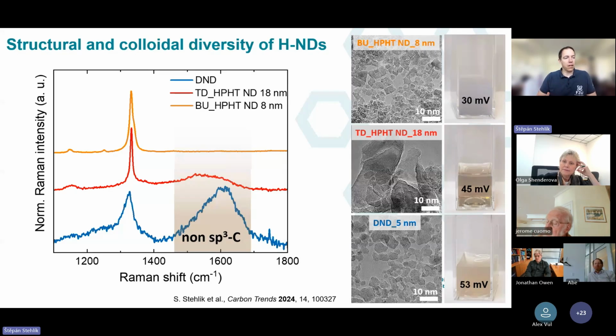So that's why we always try to keep the same amount, so then the results were comparable. So that was one thing. The parameters were, I think the heating rate was about 5 degrees per minute. The ramp was typically 6 hours. So we always somehow do the 6 hours, to be on the safe side, but quite probably 1 or 2 hours would be enough, but we are keeping with the 6 hours. And then the cooling is just we turn off the heating, so it's a natural cooling. And what is also important, we are using the atmospheric pressure of the hydrogen. So it's pure hydrogen, no dilution of anything. Not atomic. Yeah, no. It's just pure hydrogen gas at atmospheric pressure, and that's it.